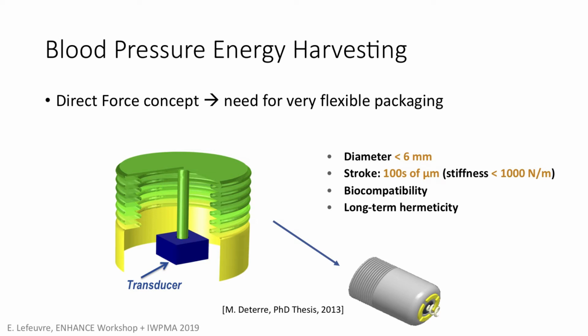So let's come back to the blood pressure energy harvesting concept. If we want to bring this into play, what we need first is a very, very flexible packaging, because we want to have large deformation and the pressure variation, the delta P, is not that big. The diameter is less than 6 millimeters, and the stroke is about several hundreds of micrometers. So if we make a rapid calculation regarding the pressure, the stiffness should be lower than 1,000 Newton per meter, which is relatively soft.